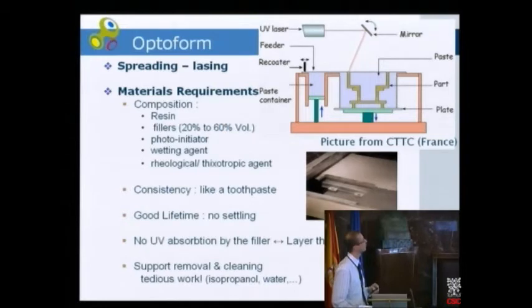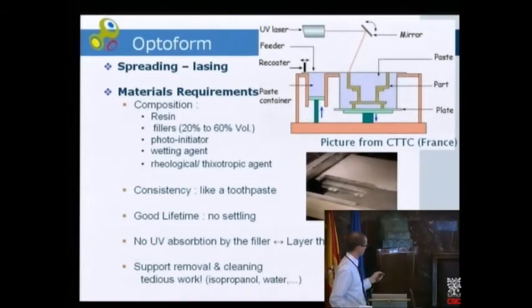And there is another problem that appears with this technology. The fillers can't absorb the UV ray, because it would lead to a phenomenon we call the screen effect. If the filler absorbs the UV laser, the energy contained in the UV laser isn't used to polymerize the paste. Thus, we will have polymerization only on the surface of the paste bed, but not inside the paste bed, and we won't have a good reaction between the layers, and the part will collapse after building.